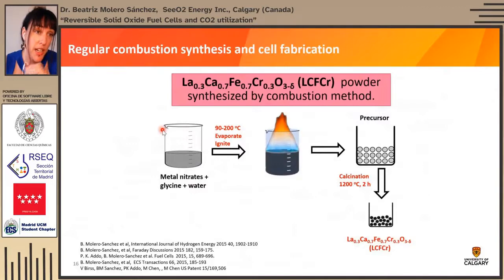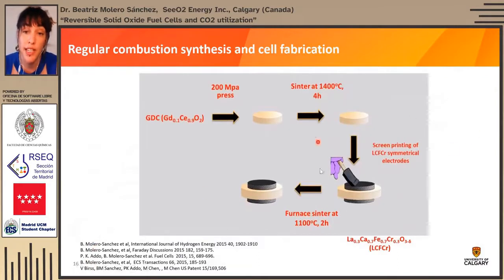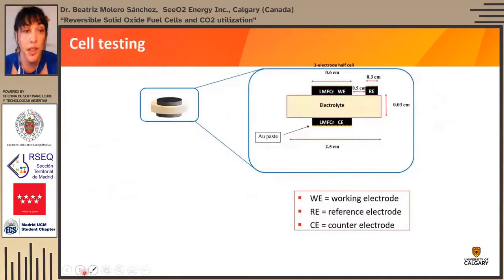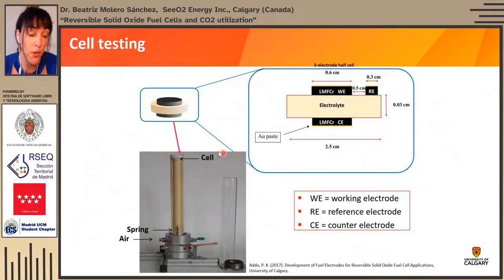So these materials were synthesized by regular combustion synthesis, and then we would fabricate the cells ourselves, as I mentioned, in the symmetrical configuration by screen printing the electrodes on both sides. The way we perform our testing, there are different configurations, but here I'm showing a 3-electrode half-cell configuration where we have the working and the counter electrodes. Again, we have the same material and reference electrodes, and this is just a picture of the setup that we were using on those devices.